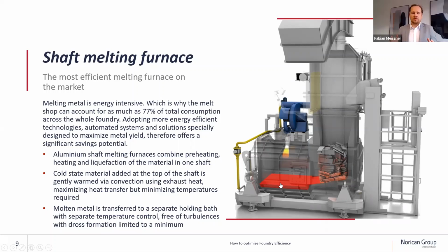than if you just, for example, an alternative technology would be you take the material, the aluminum, and you put it on a ramp. On the ramp, you don't have this preheating effect. You are taking the burners and you're directly impacting the material. This needs more energy because it's not preheated, and it also generates more oxides, because if you directly hit the material with the flame of the burner, a lot of oxidation is created.